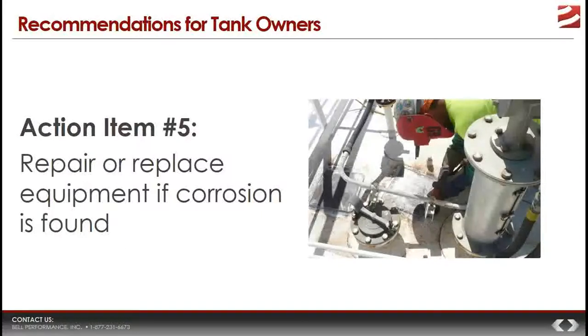But what matters is when you start adding other factors in. You start getting localized oxygen pockets. You start getting sulfate-reducing bacteria producing hydrogen sulfide. You start getting things happening in that tank that accelerate that rate of corrosion by up to 70 times. And if that happens, then you go from 0.5 millimeter per year to 35 millimeters per year. And those are the kind of situations you hear about that sound crazy. Like the one where they had an 1/8-inch 304 stainless steel plate in the tank, and it was perforated by microbial corrosion in less than 1 month. That's unusual, but it does happen. So those are some guidelines as to how quickly corrosion can happen in your tank.